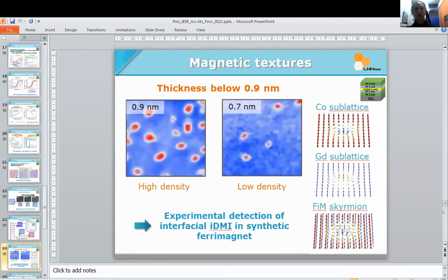So we had these skyrmions in two samples, at 0.9 nanometer and 0.7 nanometer. What is interesting to see is that the density of skyrmions is quite different. We have a higher density for the one that is a little thicker, at 0.9 nanometer. When we continue to reduce the thickness, we have a lower density of skyrmions. We observe these skyrmions from the surface, but remember that they are part of coupled skyrmions: one skyrmion in one direction on the cobalt sublattice, and the opposite one formed by the gadolinium sublattice. So through MFM, we were able to have an experimental detection of interfacial DMI in synthetic ferrimagnets.